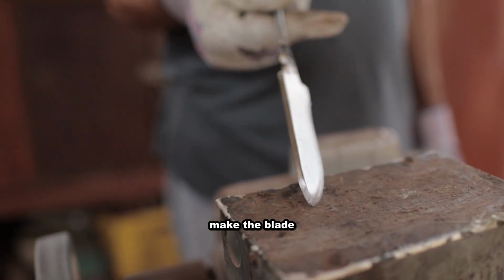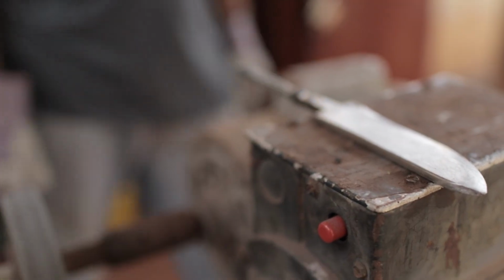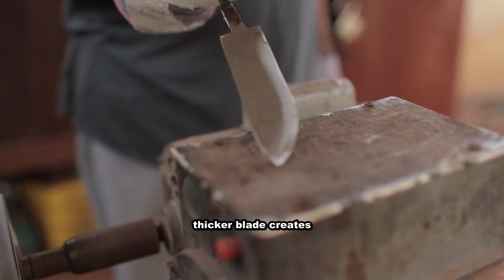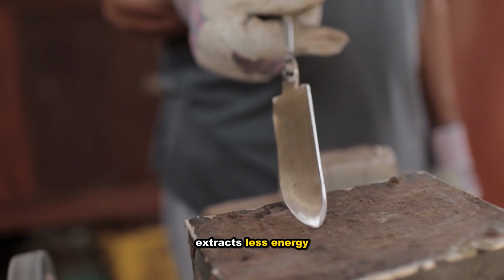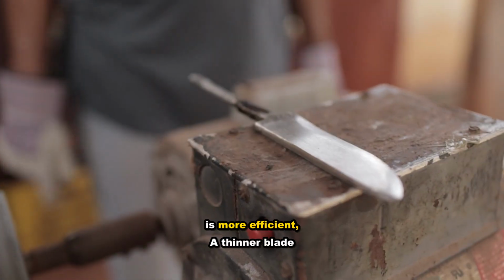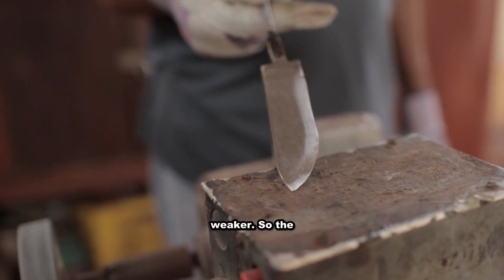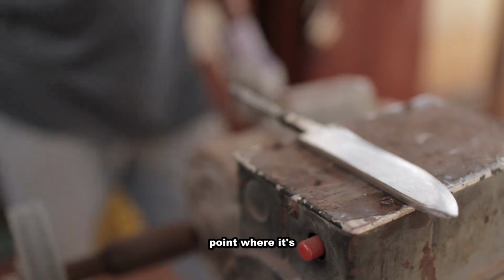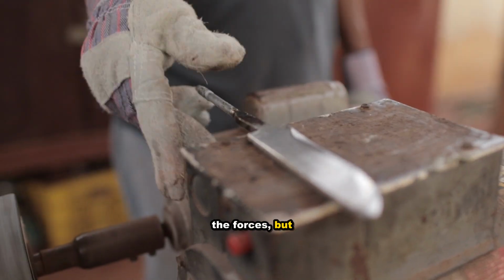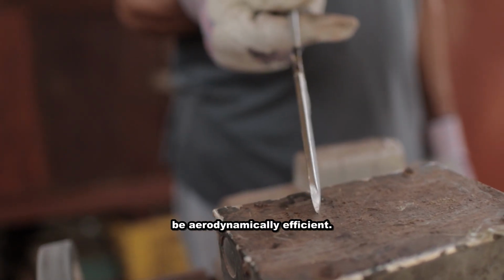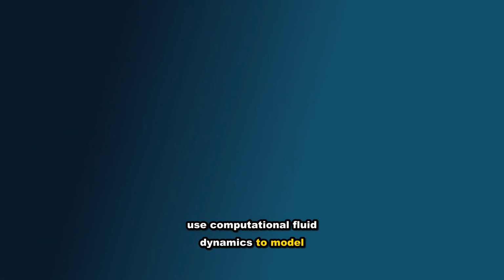Here's a question that might seem obvious, but actually isn't. Why don't we just make the blade thicker? The reason is not structural, it's aerodynamic. A thicker blade creates more drag, which means the turbine extracts less energy from the gas. A thinner blade is more efficient, but it's also weaker. So the blade thickness is optimized at the point where it's just barely strong enough to survive the forces, but thin enough to be aerodynamically efficient. This is why blade design is so critical. Engineers use computational fluid dynamics to model the exact flow of gas around the blade, then use finite element analysis to model the stress distribution. Then they iterate until they find the shape that balances strength and efficiency.